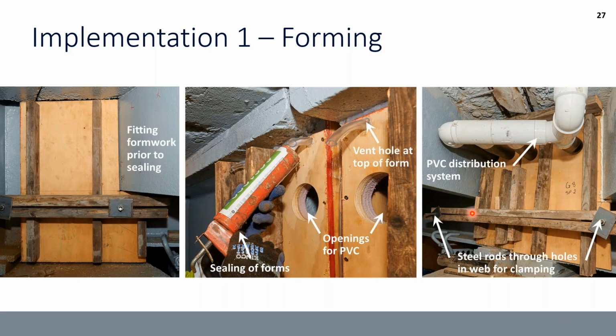With the forming, you can see this is once the decision was made to cast fully to the top of the flange, just a standard plywood forming. This is something that the contractor was great at. I do want to just point out that here we did have rods going through the web of the beam in 2 locations to tie those down to make sure that we weren't going to get any sort of blowout of the UHPC. We also had vent holes at the top of the form, and those got plugged once the UHPC was reaching the top. And just doing some simple kind of silicone sealing.